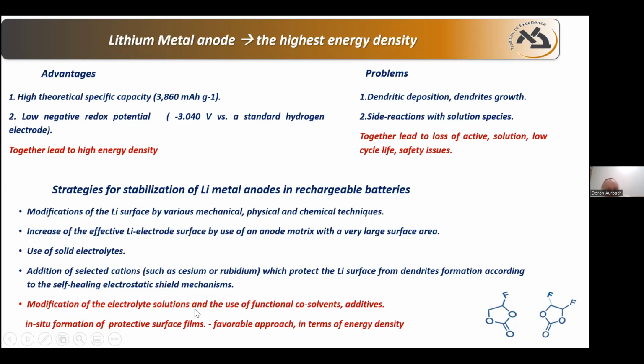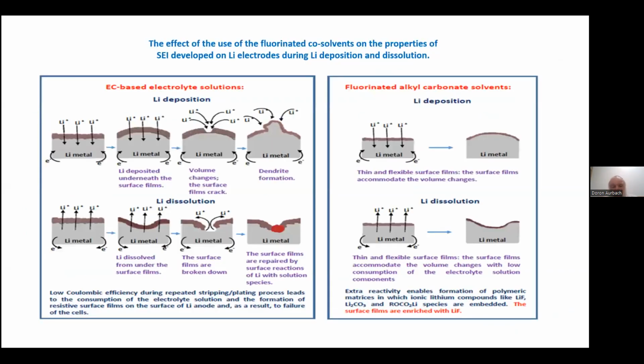Our favorite is this one. And there are several, I listed here several options. You can read it. But it appears that using electrolyte solutions which contain functional co-solvents, mostly fluorinated co-solvents like FEC and DFEC, these very reactive molecules react on the surface and stabilize the lithium surface very nicely, and we can have very nice stabilization.